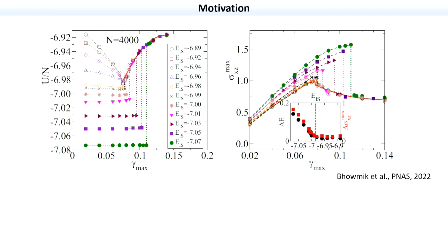So they indicated here, they are plotting the potential energy of the particle. So what they do? They apply a shear, bring it back because it's a cyclic shear, and they minimize energy in each step. Now they find the potential energy in the final configuration. Okay. So now as you anneal the system, this potential energy goes to a lower and lower value. So the system becomes more stable as a function of annealing.